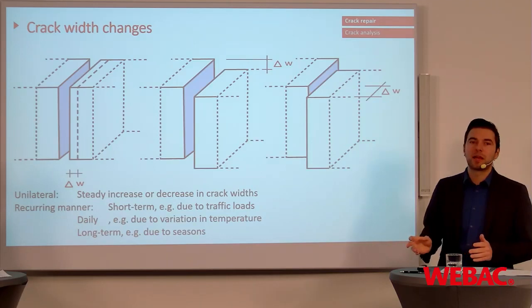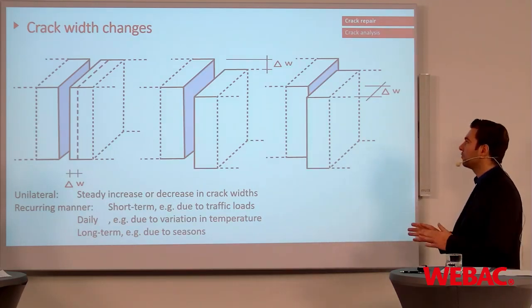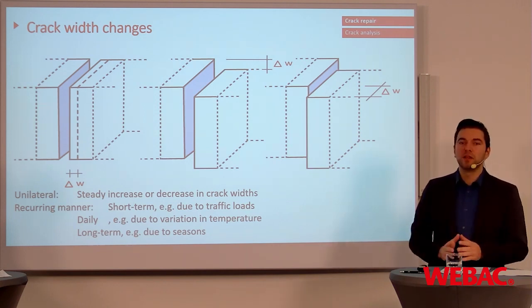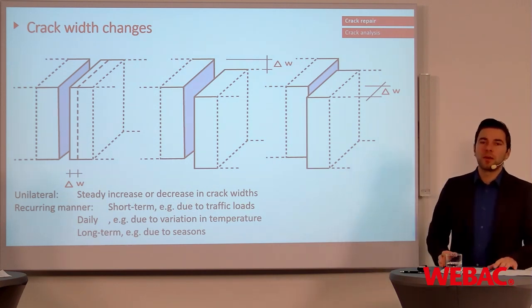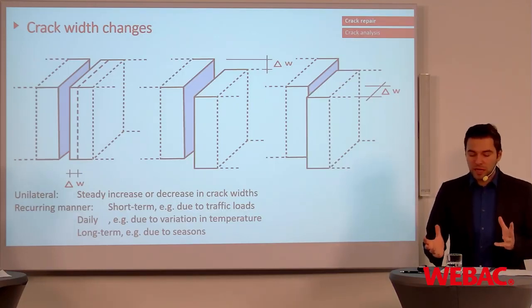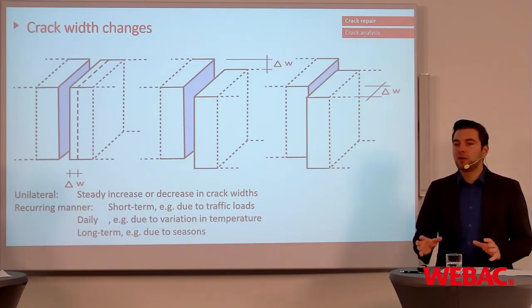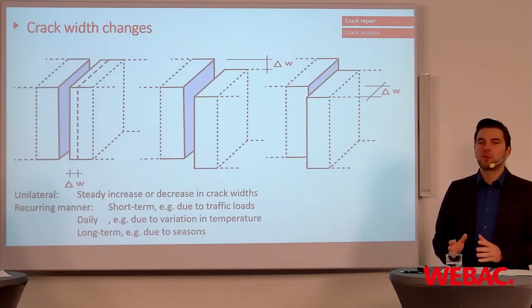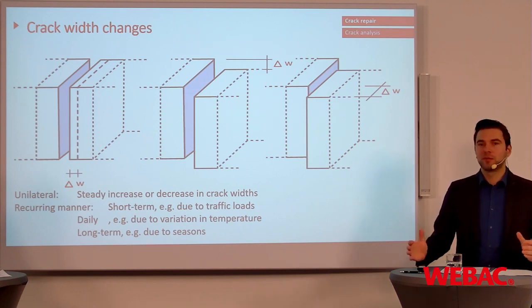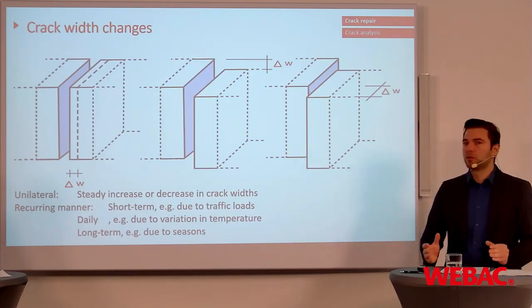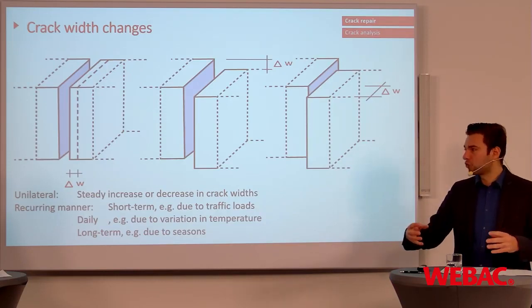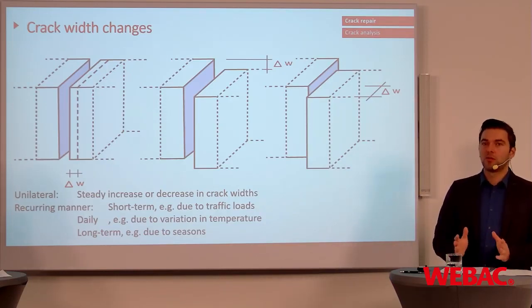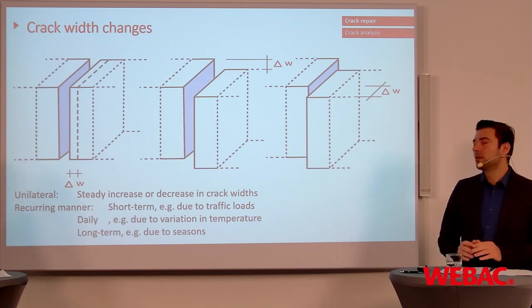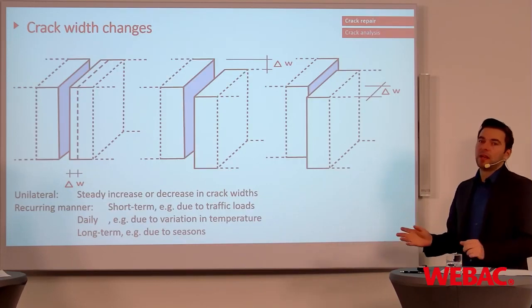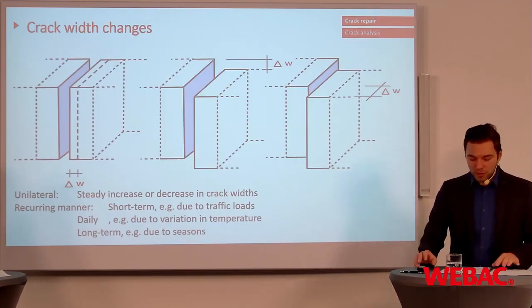Also, as you can imagine, there can be crack width changes, and depending on the changes, you need to see when the best time is to inject the crack. The most common or the most known area where you can see it is the bridge deck. So you have the expansion joints, and for sure, in summer times when it's warmer, the concrete is a little bit wider and the expansion joint is smaller than in winter times when the concrete is cold and shrinking once again. So the expansion joint is always a good indication about the crack width changes, and you have to be aware of that and keep these changes in mind when you carry out the injection.